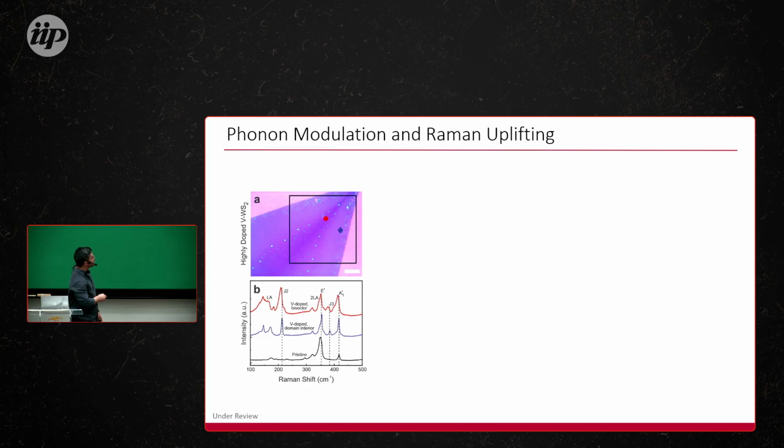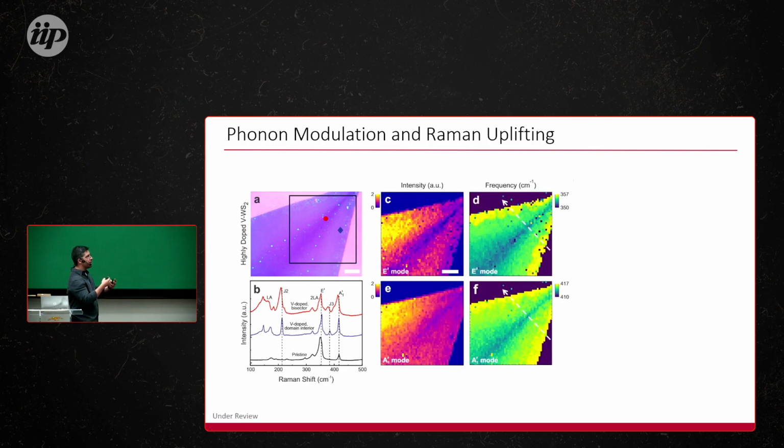You can see this mode when you have this kind of transition metal chalcogenide. The defect band is this one over here. This is an indication that we truly have the introduction of defects into the lattice. The interesting point here is that it seems we have a formation of some kind of VS2 material. So we have the WS2, but we also have the VS2.